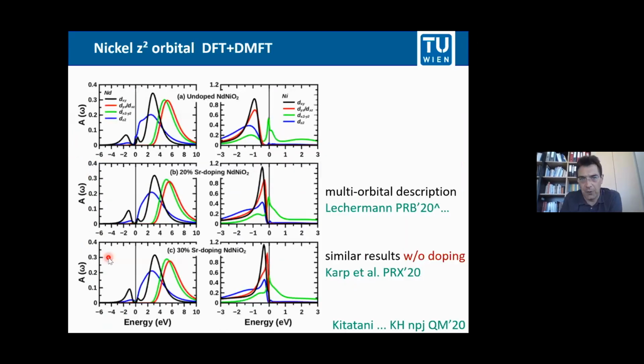Next, how about the Z-squared orbital? So we have done here, these are the K-integrated spectra now of DMFT for the neodymium and for the nickel d orbitals. And what you see here is the undoped, the 20% doped, and the 30% doped compound. And you see the undoped compound, it's a one-band structure. Only the x squared minus y squared orbital in green goes into the game. If you dope it, the other bands move up, but at 20%, it's still safe to say you have a one-band picture. At 30%, you are just at the crossover regime where the other bands start to come into the game. Let me mention that similar results also have been obtained by Karp, Andy Millis, and others, at least for the undoped compound. We have also done the doping calculations.